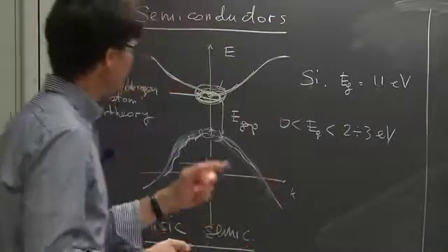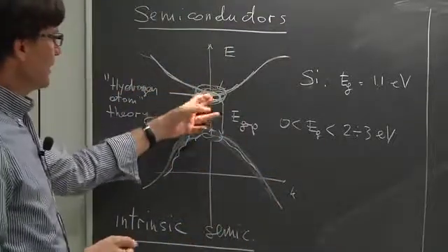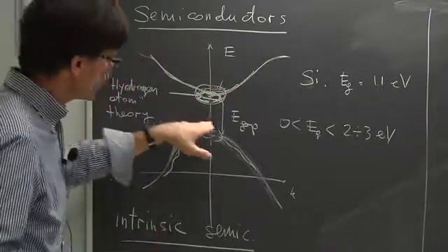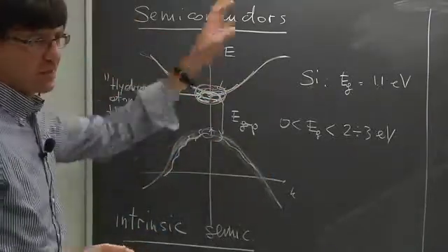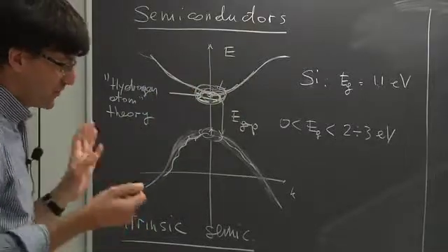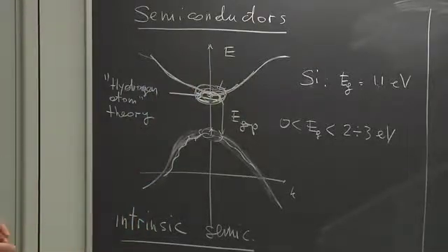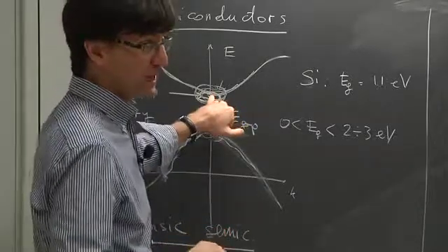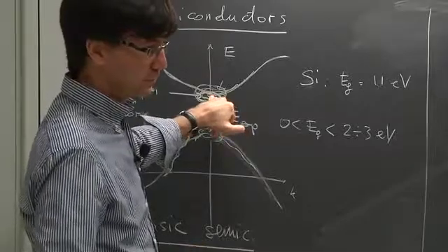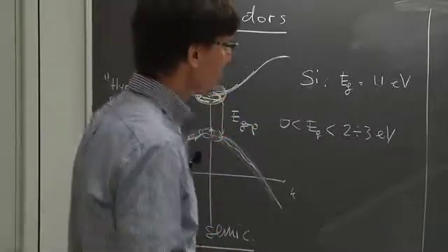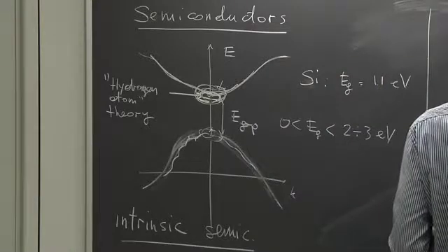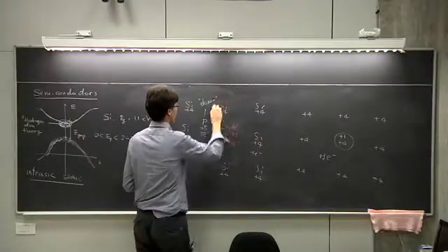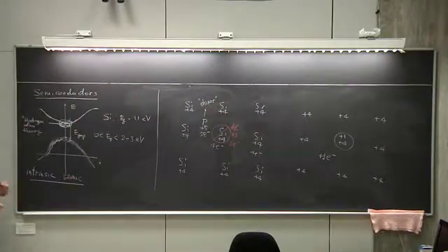Adding a phosphorus atom is going to just introduce an additional electron in the conduction band of the system, plus it's going to also introduce a small change in the shape of the bands. But to first approximation, I can actually neglect these changes of energy. The main result is that I've added an electron here in the conduction band. Phosphorus is also called a donor because it donates electrons to the conduction band.